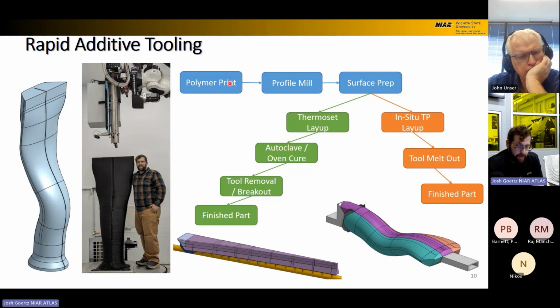Pictured here are some of the different paths you can run using this technology. So we do the polymer printing of the tool, profile mill it with the same machine, do a little bit of surface prep, and then we can go one of two directions. You can either do an in-situ layup with a thermoplastic, which will stick to the ABS tool pretty well, get as good of in-situ consolidation parameters as you can on there, and then melt the tool out, and you end up with a finished part straight off of one machine.